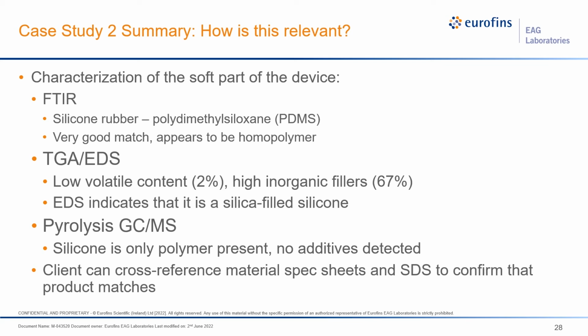So what can we take away from our second case study? Again, FTIR proved to be a great technique right off the bat to determine the bulk chemical composition of this, and it looked like it was a silicone rubber. From TGA and EDS, we saw that this had a very low volatile content and a high amount of inorganic fillers, which with the EDS analysis led us to believe that it's silica. So it's a silica-filled silicone.